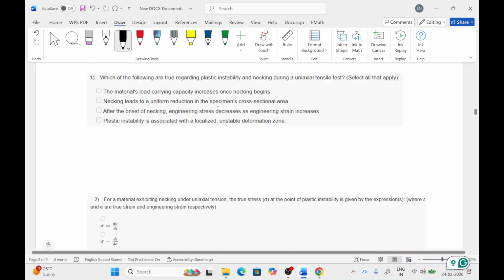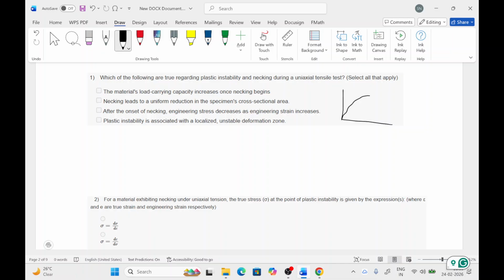So, the plastic instability and necking during a uniaxial tensile test, we can show like this. This is up to UTS, and this is the fracture of the material. This point is known as the plastic instability point. Up to this point, the material deformation is uniform, meaning if we deform this material, it will elongate with a uniform cross-sectional area.